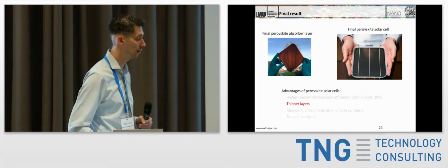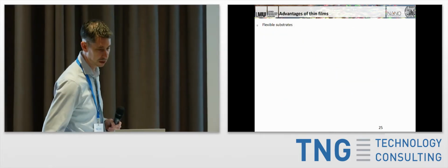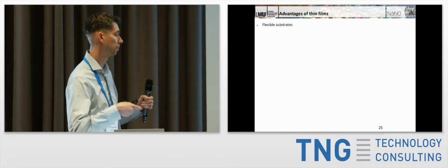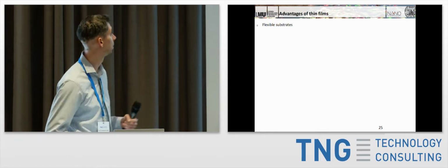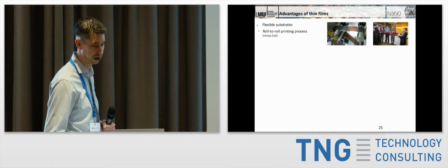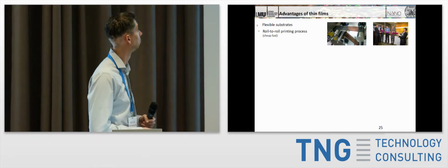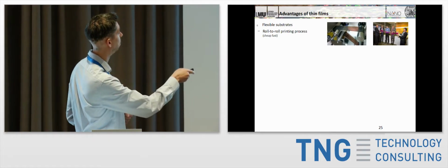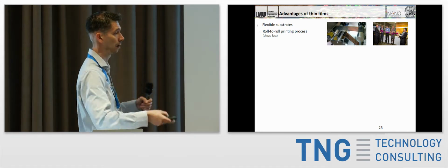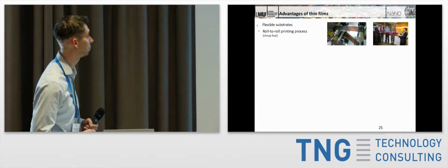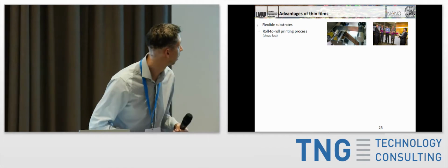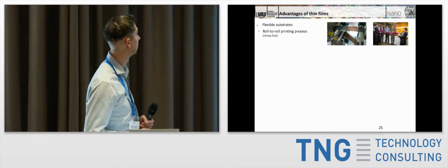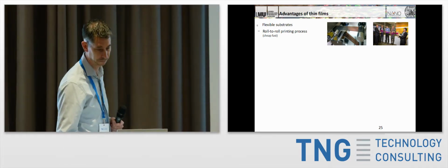All right, so why is a thin layer actually interesting? Basically, now you don't need a very rigid substrate to hold all of this load, but you can actually start to use flexible substrates. That means you can do roll-to-roll printing, where essentially you have a polymer substrate that gets printed on just like people do with newspapers, if they are still printed nowadays. And so that makes the process a lot faster and a lot cheaper.